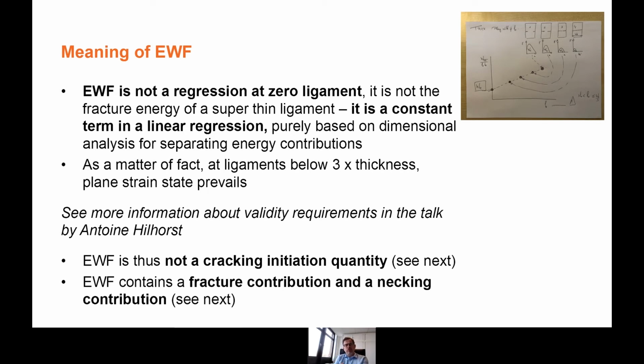Through dimensional consideration, you find that the total work is the sum of a constant term and a term that varies with ligament length. It does not say it's the extrapolated value at zero ligament length. Of course it is for mathematical reasons, but don't try to put a physical meaning to that. In fact, when you go to ligament lengths that are too short, the stress state moves from near plane stress to plane strain, and you lose the linearity. So this is very important: don't talk about extrapolation or regression at zero ligament length.